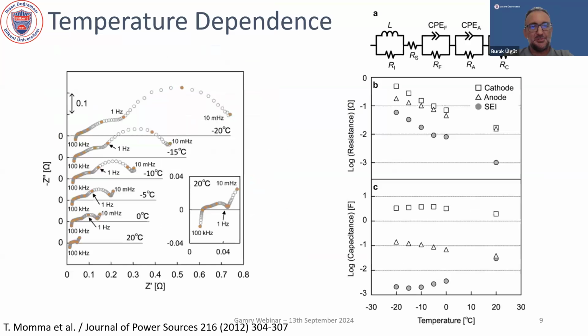So let's get started with temperature dependence. Now, clearly, I am not the first one to think about changing the temperature of a battery while doing impedance. This is the first paper that I had seen back when I was working for Gamry. This was the EIS meeting in 2013 in Okinawa. I listened to a talk by Professor Momma where they showed that they varied the temperature of the cell, took the impedance spectrum, and used this to calculate activation energies for anodic and cathodic processes. They said the changes in capacitance were minimal, and the way they plotted it looks like it, but notice that these are logarithmic axes. So the SEI capacitance, for example, is clearly significant and not minimal, but I'll talk about that in a little bit.